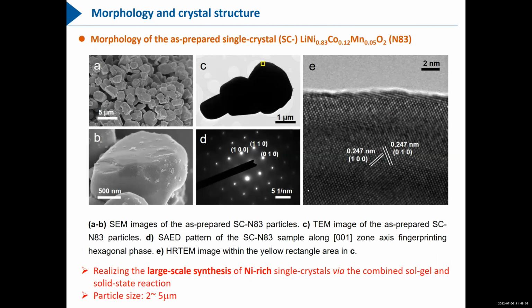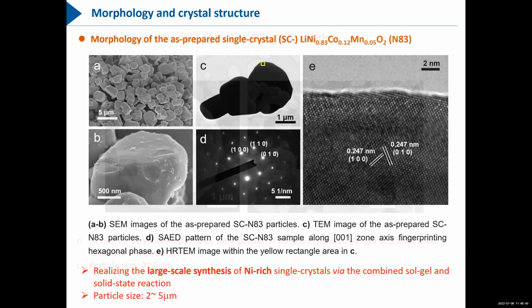First, we have realized the large-scale synthesis of nickel-rich single crystals with a combined sol-gel and solid-state reaction. The particle size is around 2 to 5 microns, and you'll find the particle distribution is very good. The composition of these materials is about 83% nickel, so we call it nickel 83, single crystal nickel 83.